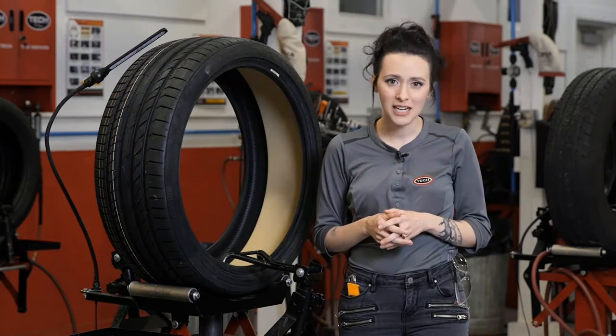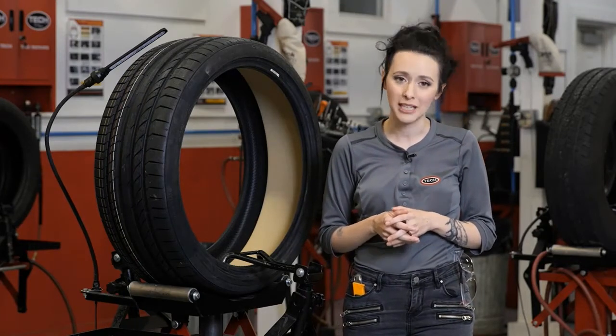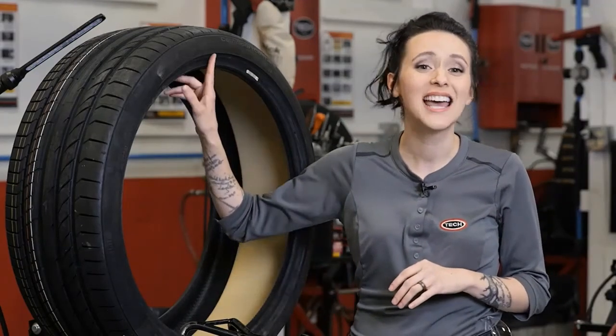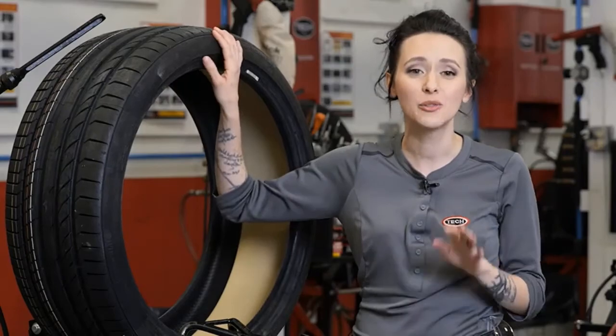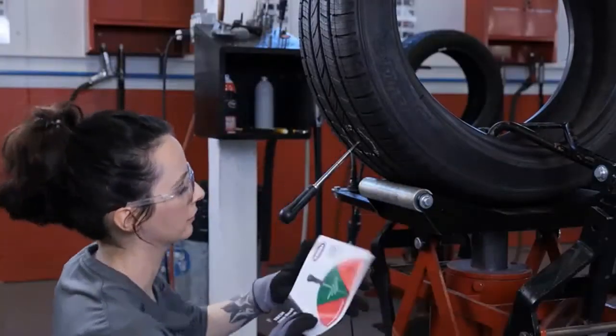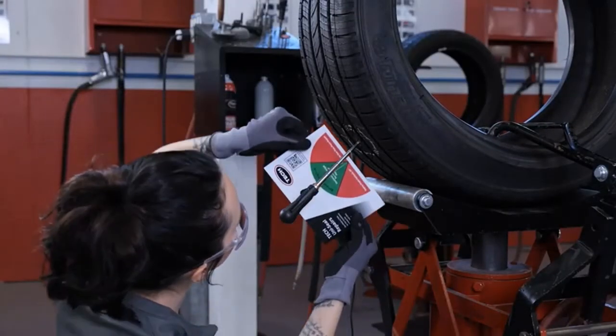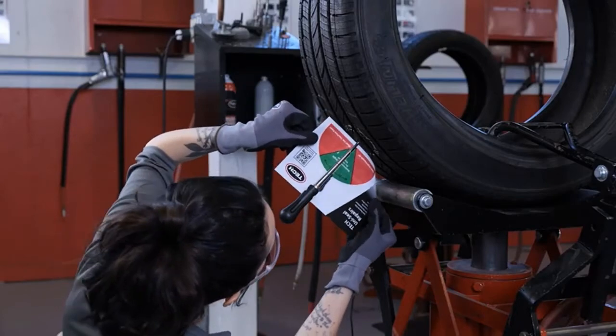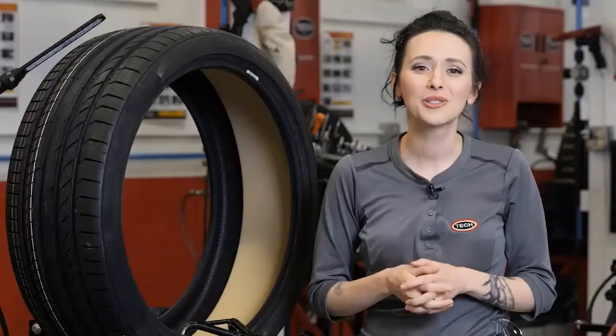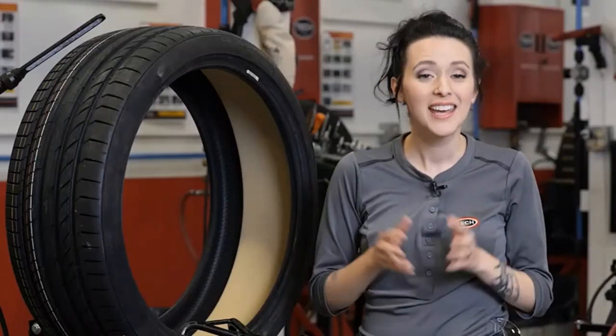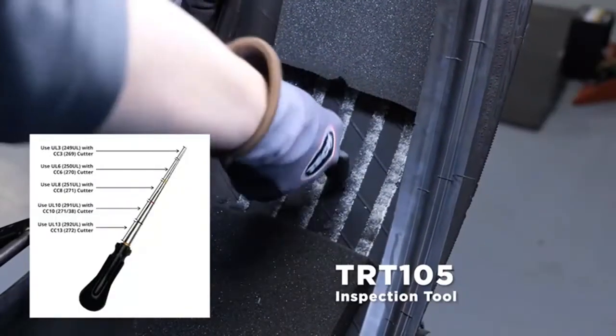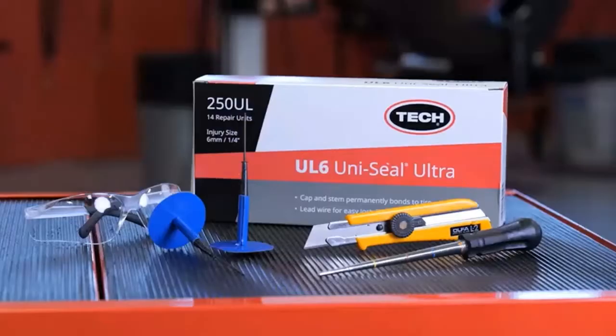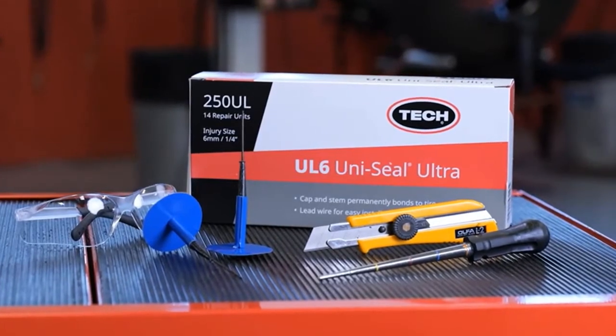Remember, the injury size and location will also determine the repairability of the tire. To be considered a puncture repair, the injuries must be located in the crown area of the tire and not exceed 1/4 of an inch or 6 millimeters after preparation. If the injury does not fall within these limitations, the tire will need to be replaced. Once again, injuries in the shoulder and sidewall areas cannot be repaired with a Tech Uniseal Ultra Repair.